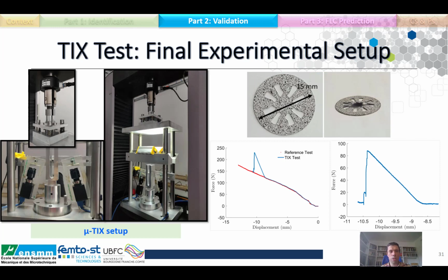To measure the punching force, we have to take into account the spring force. So the reference test is illustrated in the graphic. We first made a test without a specimen to measure the counter spring force, and then we conducted a normal test with the specimen in the system.